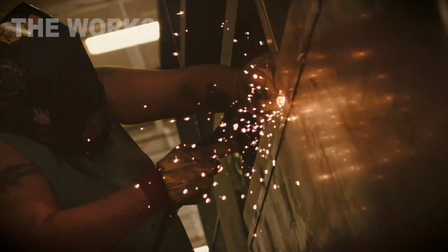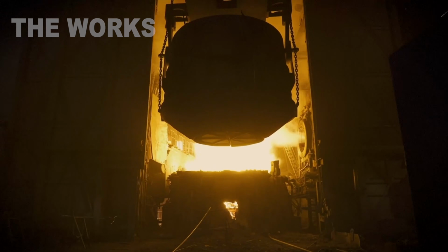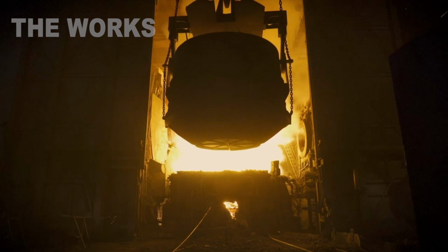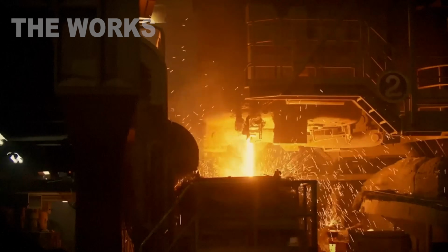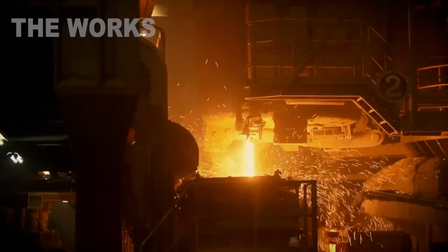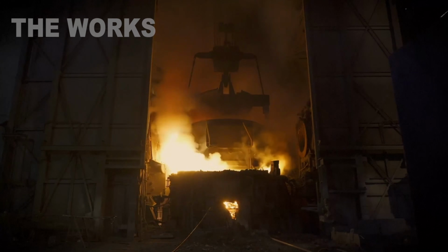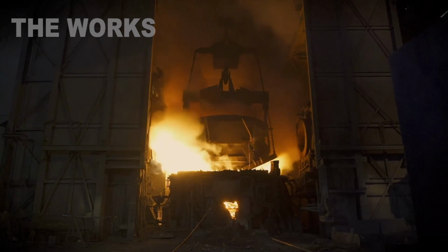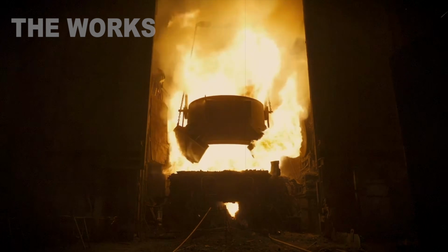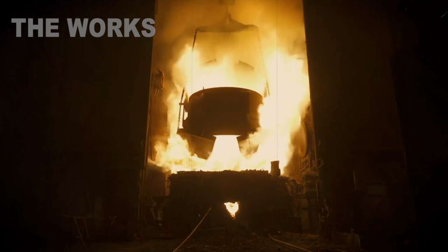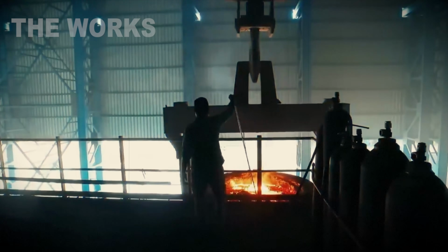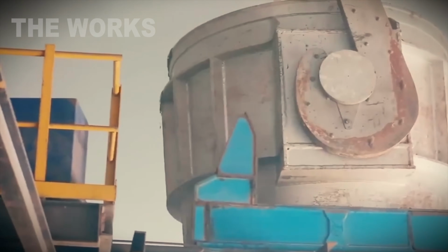Reborn in fire. High-strength steel heads to the metallurgical plant, loaded into an electric arc furnace. Capacity, 100 tons. Three graphite electrodes, 24 inches in diameter. 600 volts, 60,000 amps, 36 megawatts of raw power. An arc ignites between the electrodes and metal. The arc zone hits 6,300 degrees Fahrenheit.